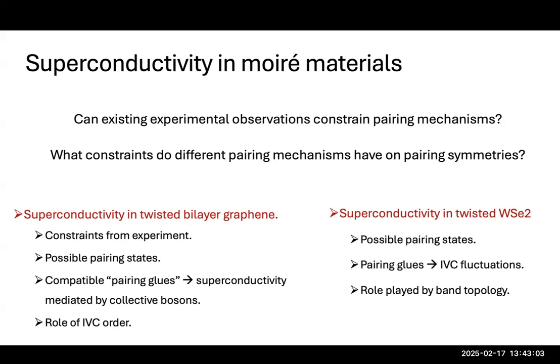And we'll see an interesting role being played by the band topology. So both of these systems have Chern bands, and in twisted tungsten diselenide, something we found is that there's a very interesting contribution from band topology on the energetics of superconductivity in this case.